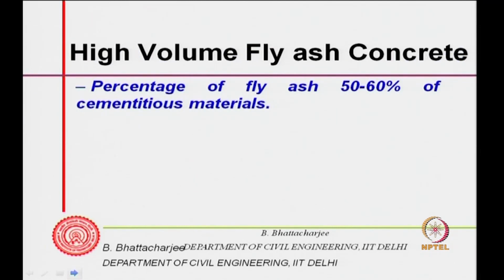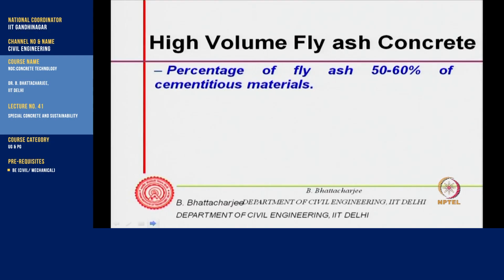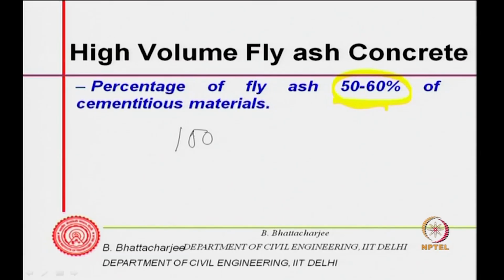Another concrete is high volume fly ash concrete. The percentage of fly ash can be as high as 50 to 60% in the cementitious material. So, you have 100 kg of cement, developed largely in North America, Canada and United States. 100 kg of cement, maybe you will have 100 kg of fly ash or maybe more, 120 kg of fly ash. So, this is the material you use.